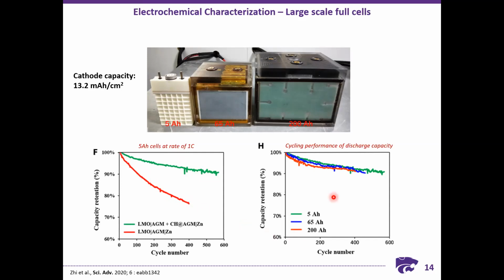So for all these cells, which are 5 amp hour, 65 amp hour, and 200 amp hour cells, they almost behave quite similarly, and they were able to achieve around like 400 cycles with a capacity retention of 90% with the 200 Ah battery, which is quite amazing.